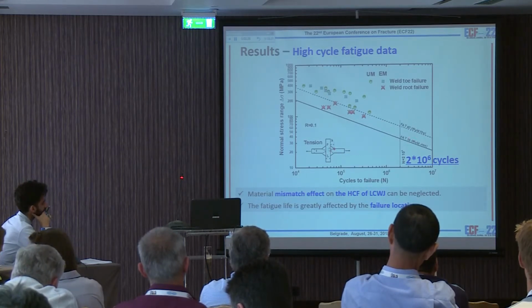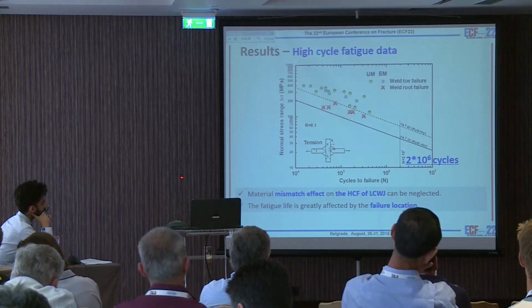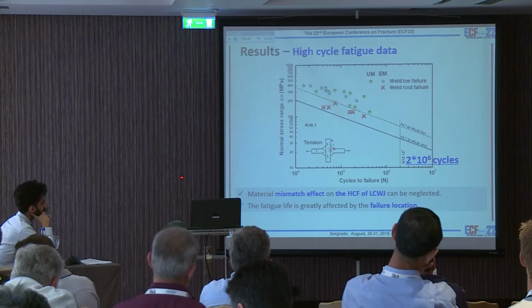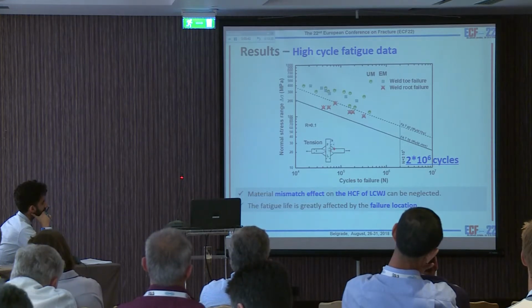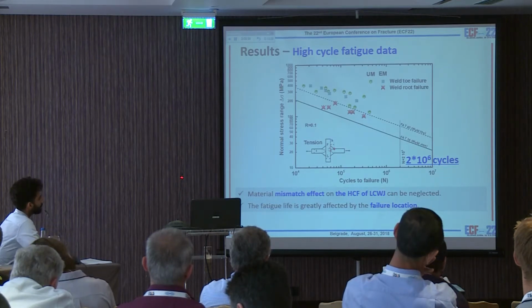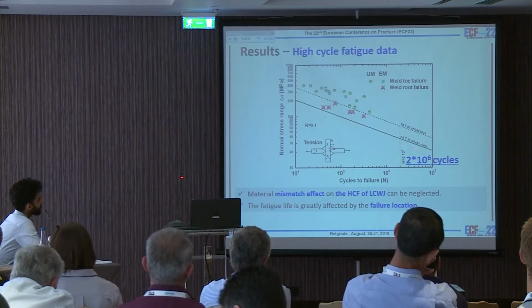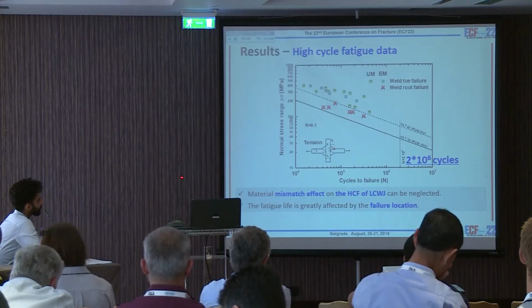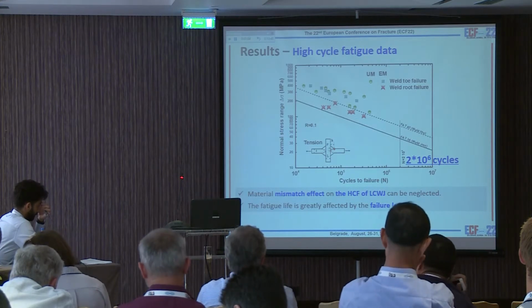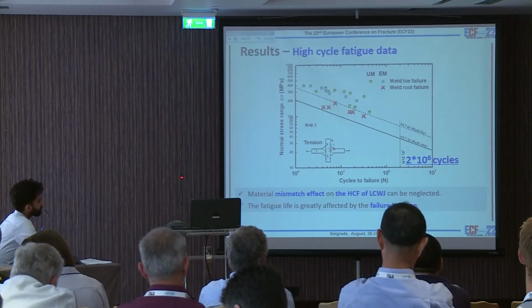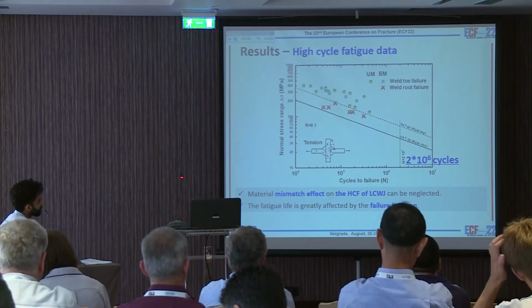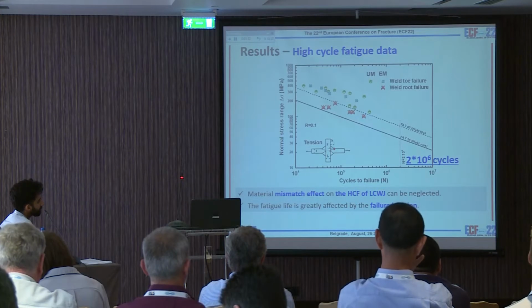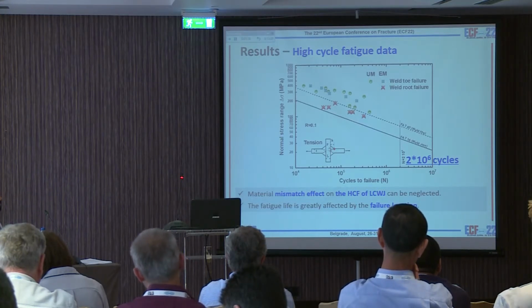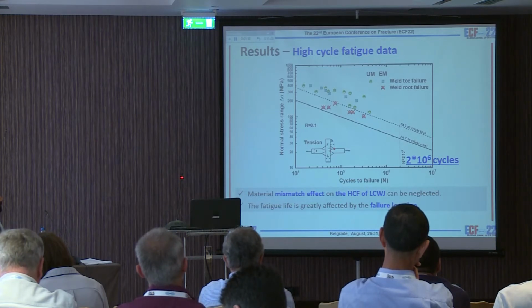So we're using the IIW standard to compare to this data. We can find the FAT 63 is suitable for the high cycle fatigue of the welded toe failure case. And then FAT 36 is suitable for the welded root failure. Then the material mismatch effect on the high cycle fatigue can be neglected. So the fatigue life is greatly affected by the failure location.